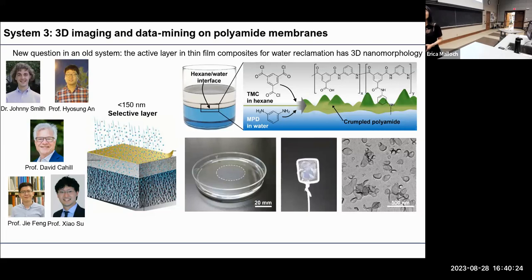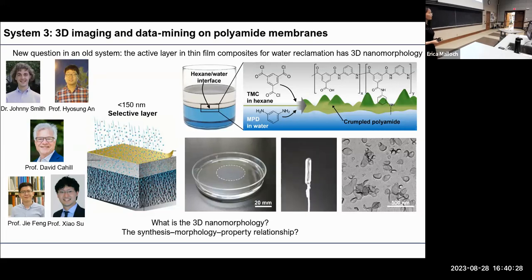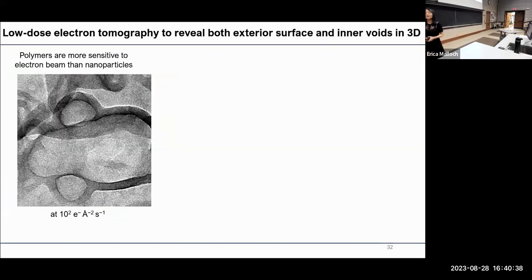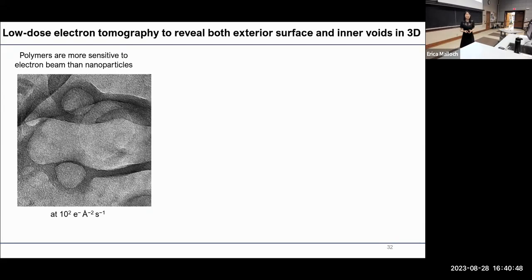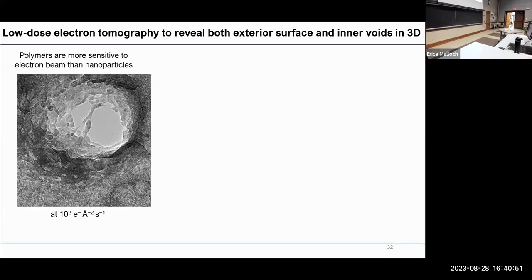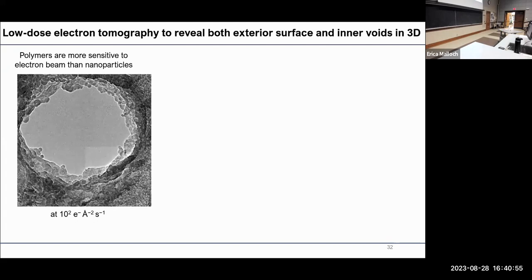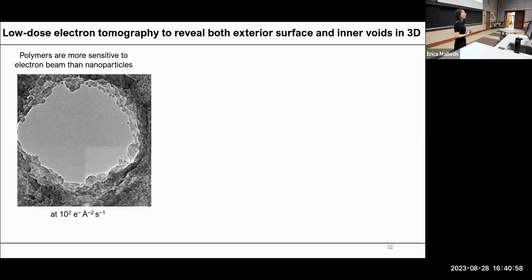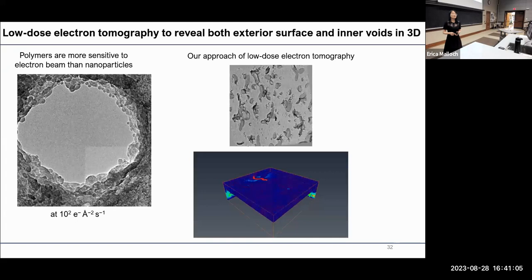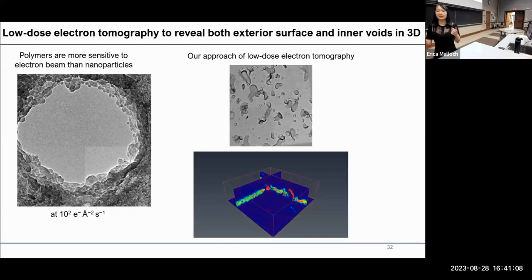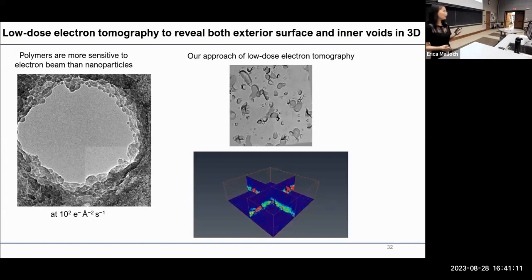So here come the new questions for an old system. What is the three-dimensional nanoscale morphology? And what is the morphology relationship with synthesis and property? As I mentioned, electron tomography is very important, but keep in mind, polymers are a lot more beam sensitive than the inorganic nanoparticles we studied earlier. As this movie shows, sometimes you can literally drill a hole using the electron beam onto the polyamide filtration membrane sample. This is when our previous expertise in carefully controlling the electron dose makes a difference. With some optimization procedures, we can now take more than 100 images of the same polymer sample at different angles without structural damage.